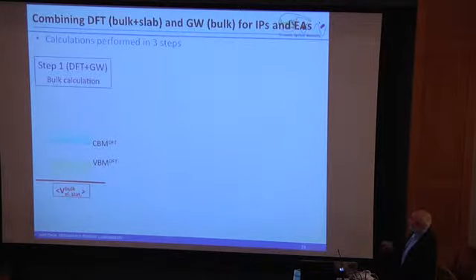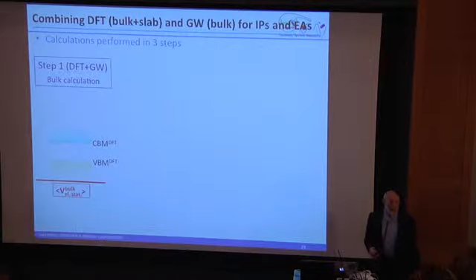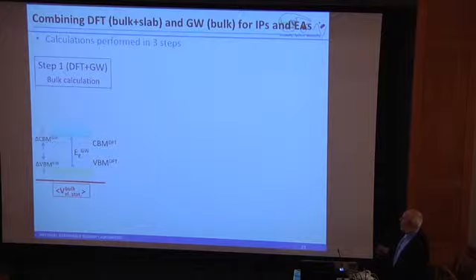We do this in 3 steps. First, we use DFT plus GW to do a calculation. If you just do DFT, you're probably aware you don't get very good band gaps normally. But if you do DFT plus GW, you get a correction for the valence band maximum and conduction band minimum, and those tend to be much more accurate.